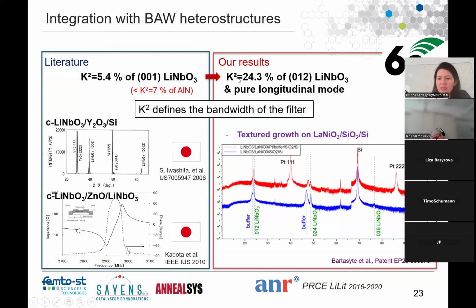So as you see here, this is silicon with a platinum electrode, which is 111. It's a sputtered platinum standard electrode, and then we grew this buffer seed layer of lanthanum nickelate, which allowed us to grow lithium niobate of 012 orientation on top. So it grows very nicely on that.